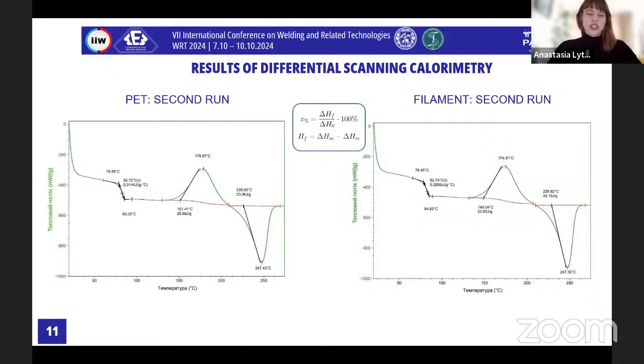So the last experiment, just to confirm the data we received in the previous experiments, was differential scanning calorimetry analysis using the DSC Q2000 apparatus. Two runs were conducted for both PET and filament samples to eliminate internal stress, as we performed before, in order to remove the material's history. So in the first run, I do not have the graphs here because we cannot take a lot of information from there. The sample was heated to its melting point, cooled down, and the process was repeated for the second run.